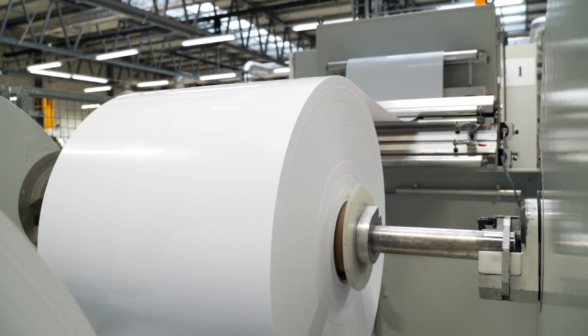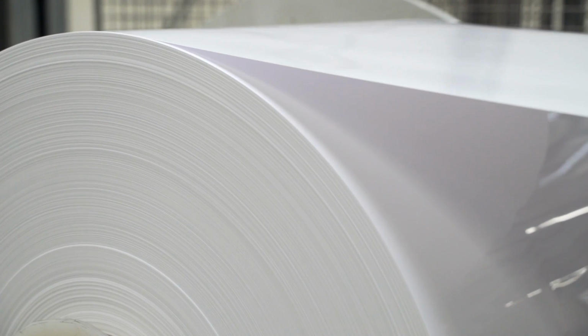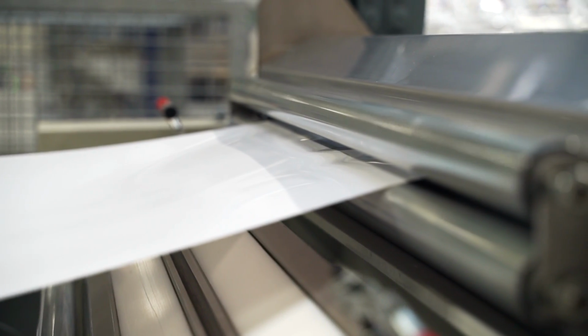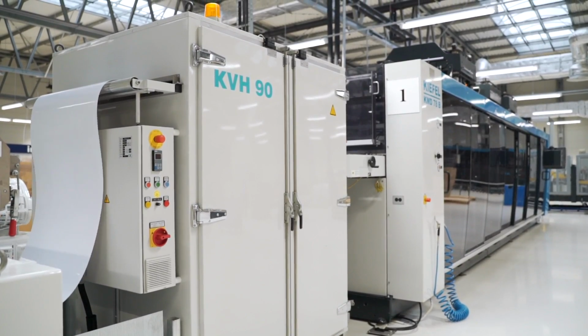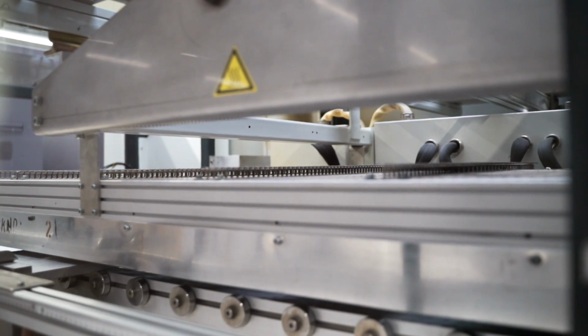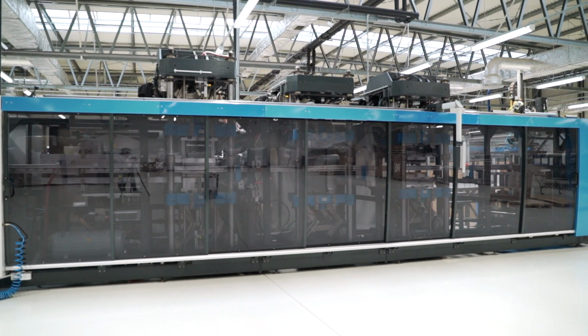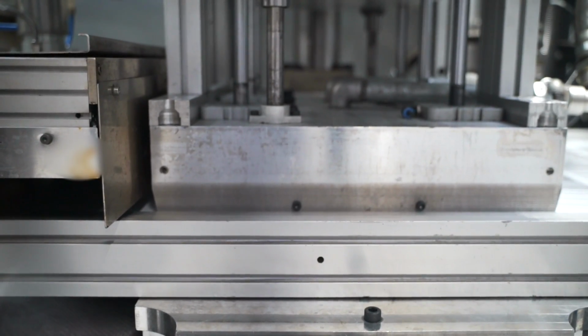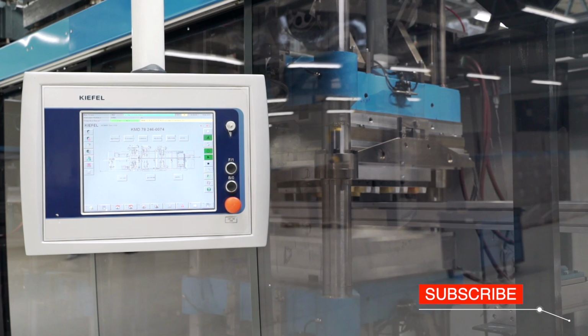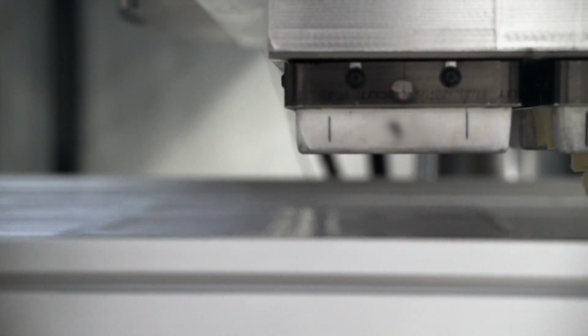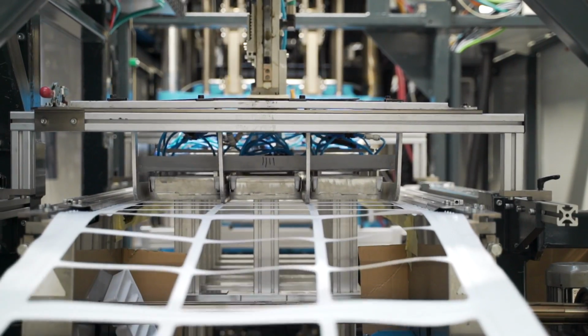The film is unrolled and then heated at the first two stations. The temperature of about 200 degrees Celsius makes the film malleable. Then it goes to the forming station. The material is initially stretched and shaped with pressure and vacuum. The material cools down and thus the shape of the detail is preserved. In the next station, individual products are cut out with the die cut. Next, they are picked up and placed by a robot.